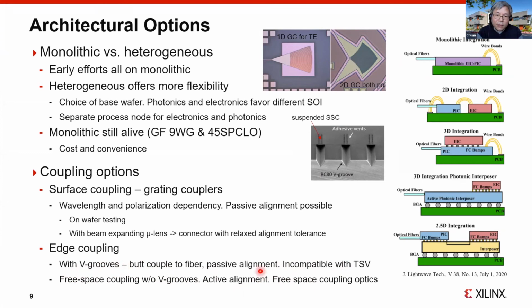Unfortunately, V-grooves and TSV are not compatible, because if you have TSV through your PIC optical wafer, then the wafer needs to be thinned, and thinning the wafer obviously is not a good thing for these edge V-grooves. Right? So these two processes are not compatible. And another approach, of course, is to just have a spot size converter to the edge of the die and do the coupling using free space optics. And this is not favorable because it requires active alignment.